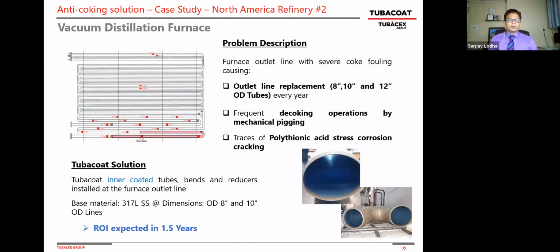This one is something we just did recently, a vacuum distillation unit furnace. This furnace outlet line had a severe coking problem. Again, it's a North American refinery where they have this outlet line replacement due to coking. These are 8, 10 inch and 12 inch OD tubes, and they have to replace them every year or every 13 to 14 months. Frequent decoking operation and mechanical pigging. A lot of traces of polythionic acid stress corrosion cracking. And we just supplied these tubes. They would be installed very soon.